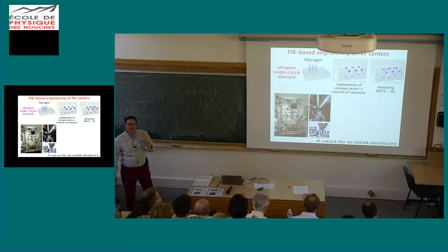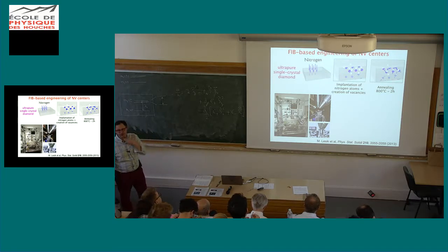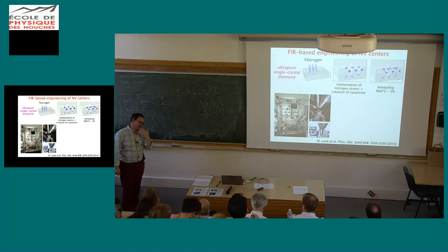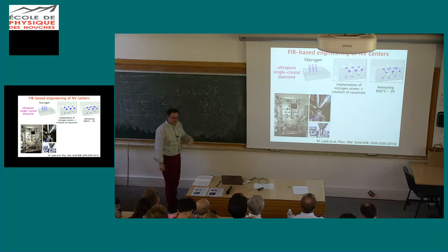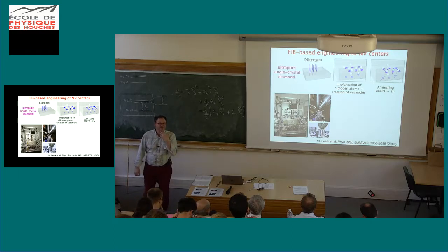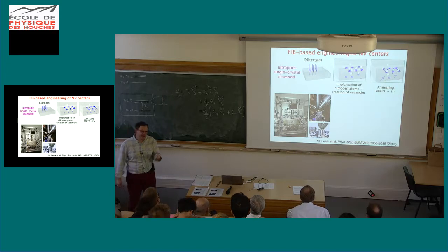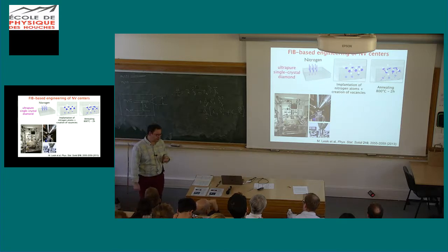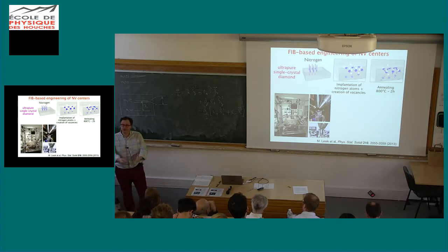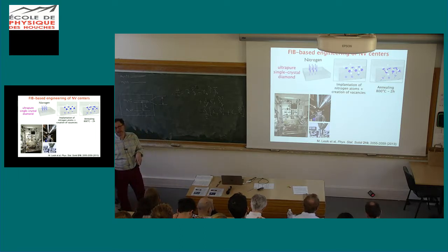The other point also is that you want to use those defects. And so can you create them? So I show you how they can be created in bulk, as ensembles, like for instance, irradiation in alkali halide crystals. A lot of new techniques have now been investigated and are available to engineer NV centers and other defects in diamond or in any wide bandgap materials by different kinds of techniques. Either you create them during the growth or you add them as extra impurities, for instance, using ion implantation.